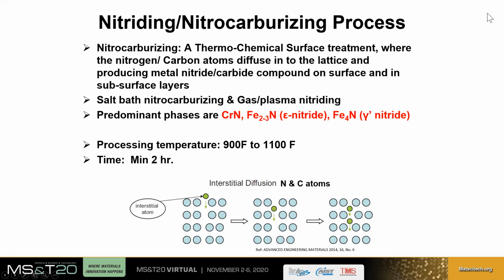Surface treatments such as nitriding and nitrocarburizing processes are some options for surface hardening of these stainless steels to improve wear and galling resistance. These are thermochemical processes where nitrogen in the nitriding process, and nitrogen and carbon in the nitrocarburizing process, are diffused in the lattice of the metals. This operation produces nitrides and carbides on the surface. In case of chromium-rich material, they form chromium nitride and iron nitride. This diffusion treatment is generally carried out at 900 degrees Fahrenheit to 1100 degrees Fahrenheit, and time of operation can vary from 2 hours to 20 hours.